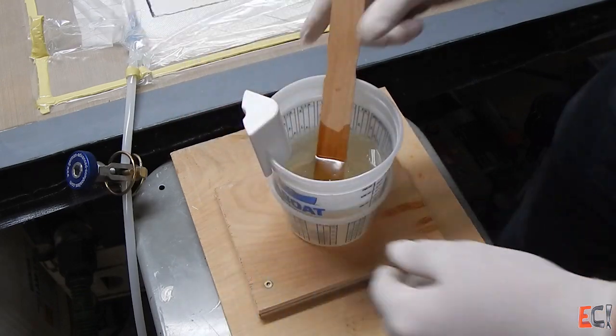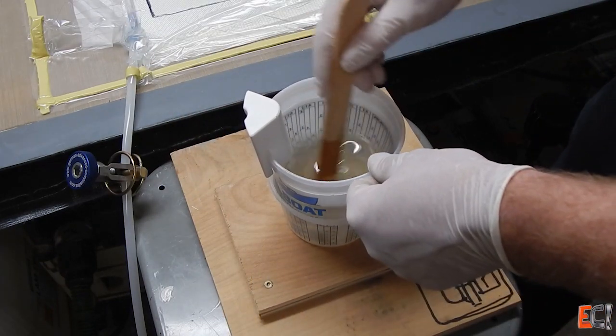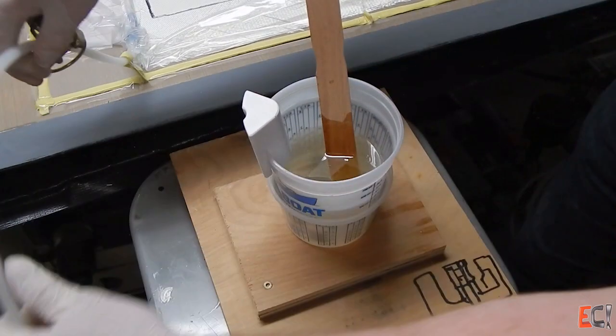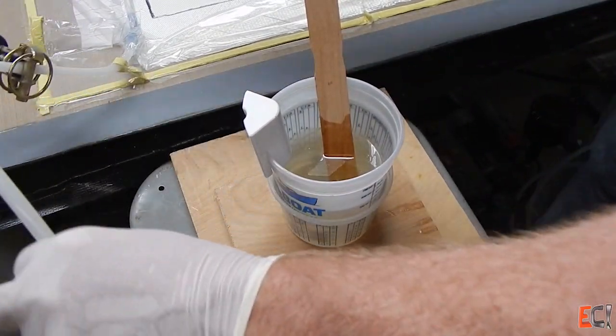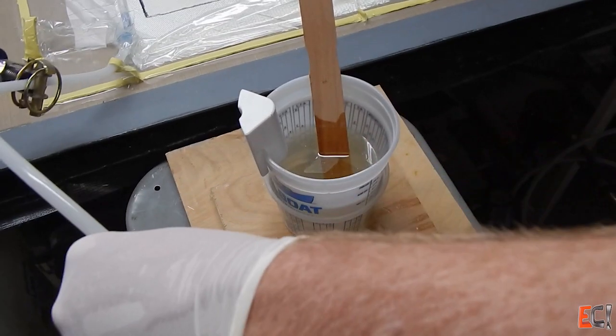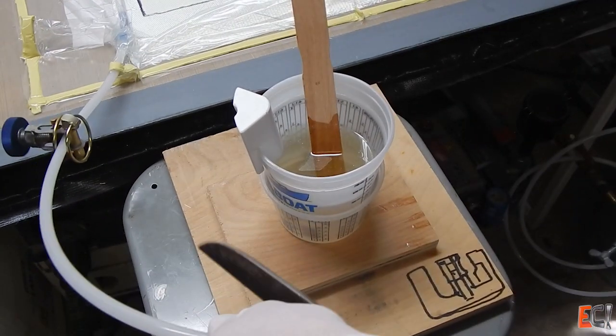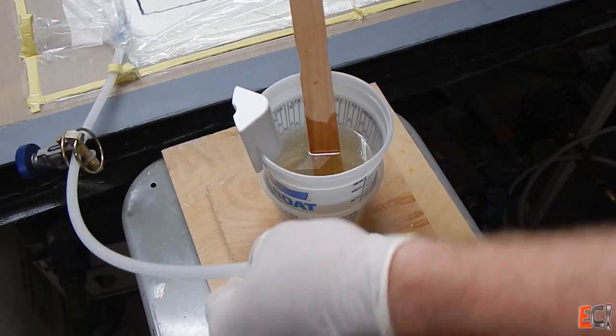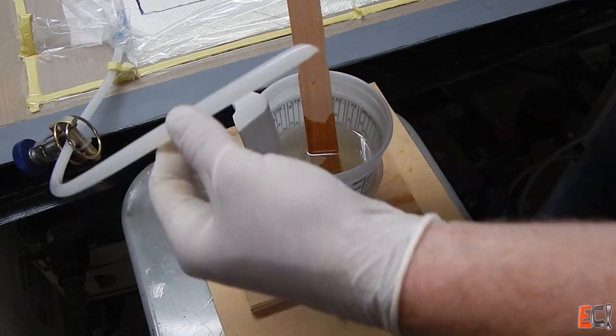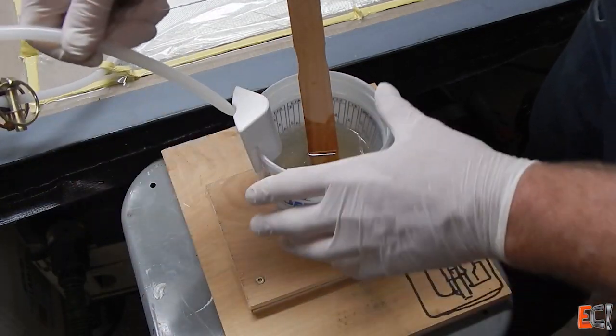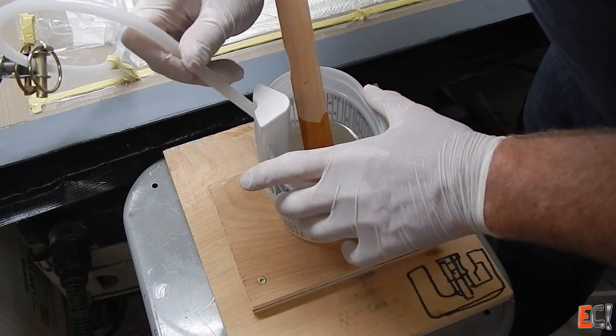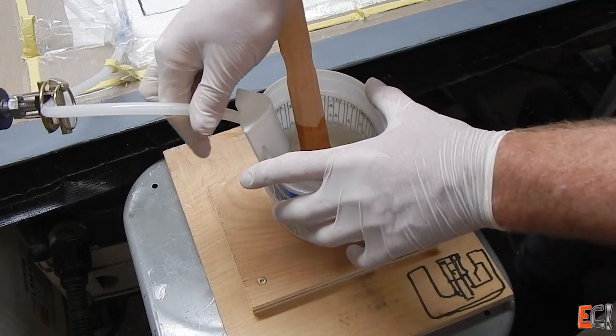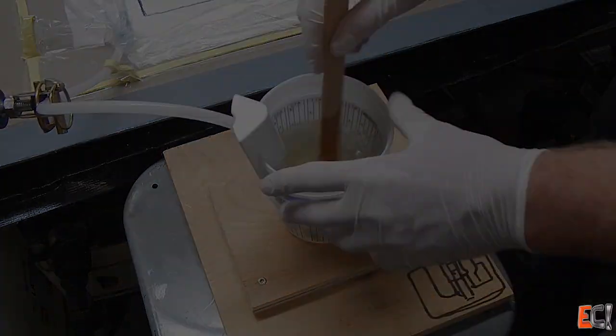And I'm using this little vacuum thing that I 3D printed that nicely clips on the edge of the bucket and holds the hose so the whole hose doesn't slip out. And cutting a bevel on the bottom of the hose, roughly the right length, so that it doesn't choke itself off on the bottom of the cup. It's a nice detail, saves you the trouble of having that problem.